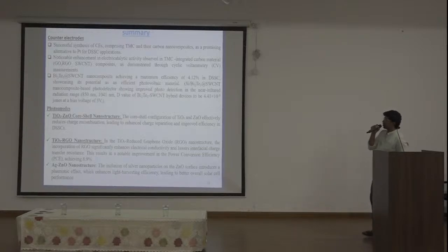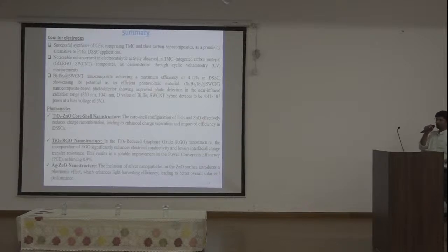And bismuth telluride based material, we have tried for the first time. We are getting a maximum conversion efficiency that is still low, but we have tried various carbon composite materials. It's ongoing work to improve how the topological material works in this counter electrode, especially in DSSC application.